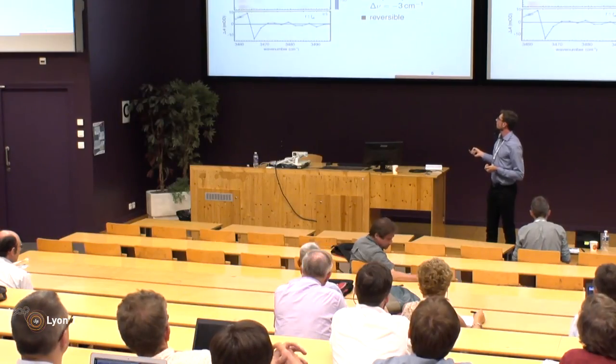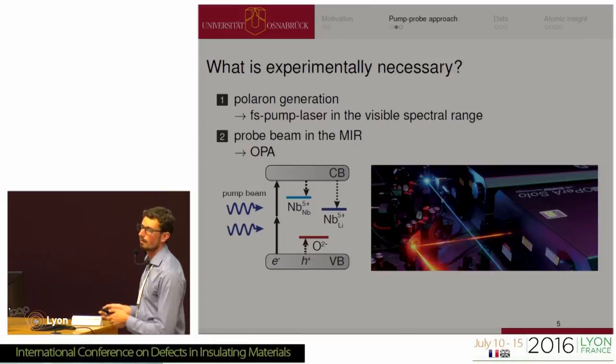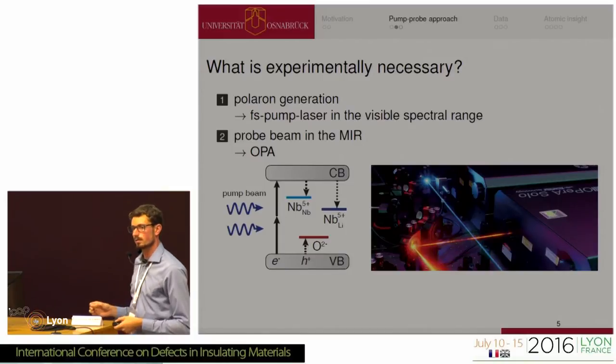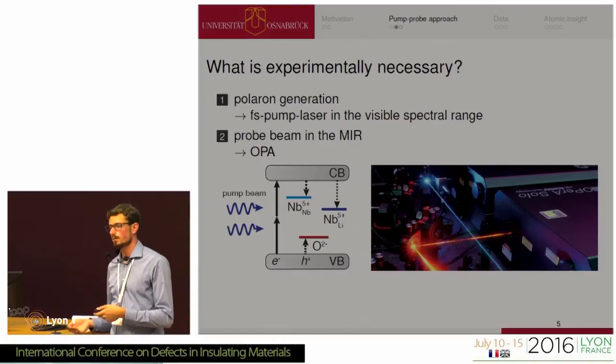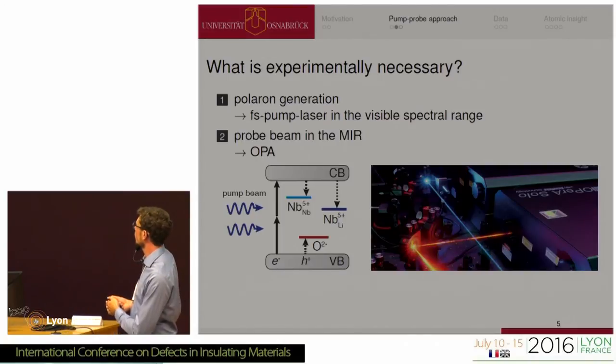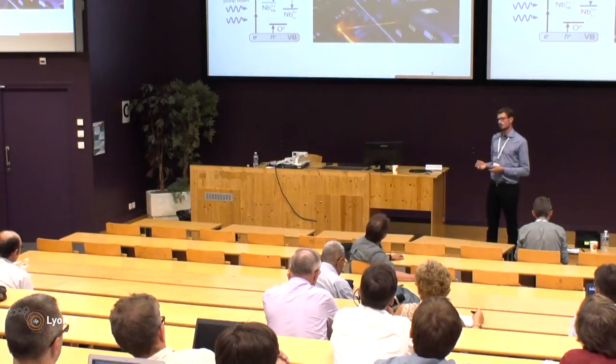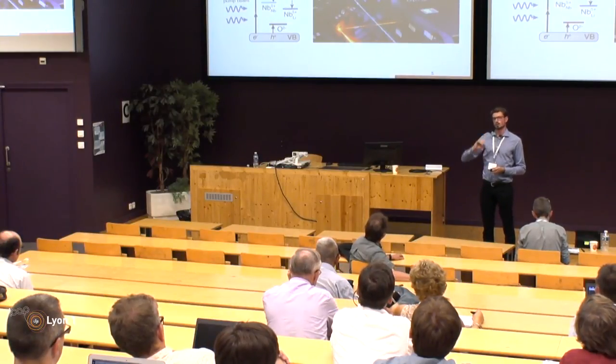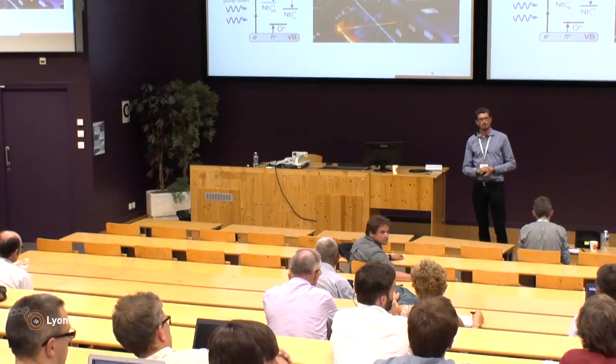So we've got niobium on lithium site, and so we've got a certain defect structure. And this leads to the generation of hole polarons. So you've got different possibilities for small polarons in lithium niobate. For example, you can have a charged carrier bound to a niobium on a niobium site, or a charged carrier bound to a niobium on a lithium site. And we are observing the lattice distortion due to a hole on an oxygen. Okay.